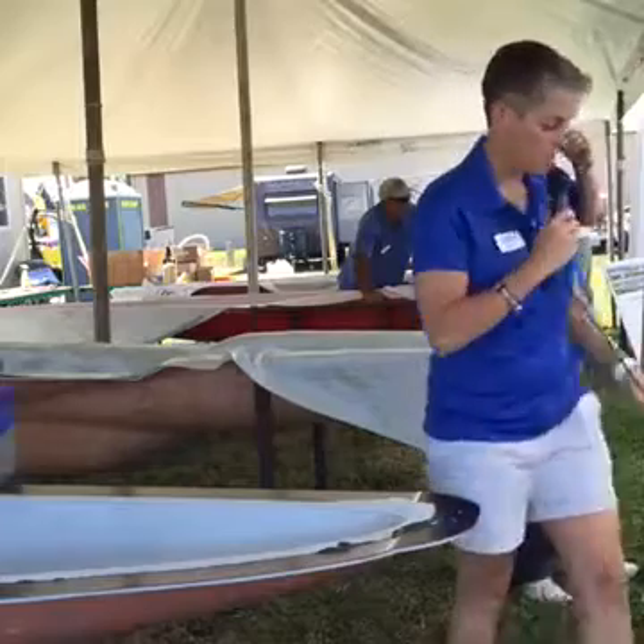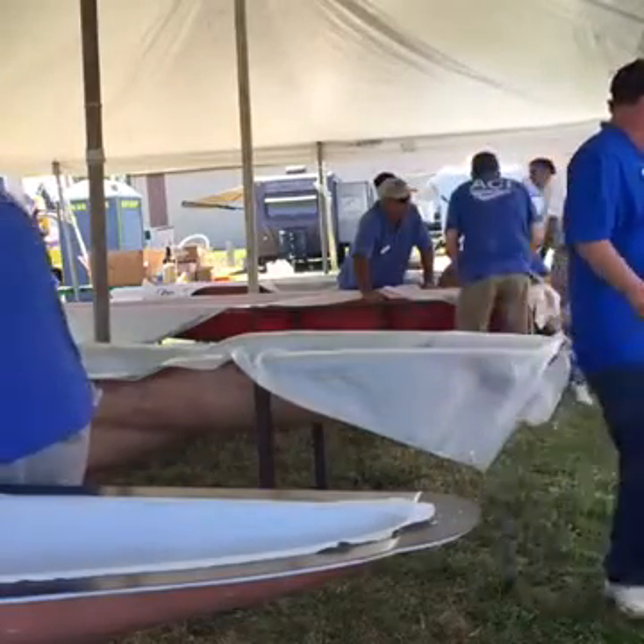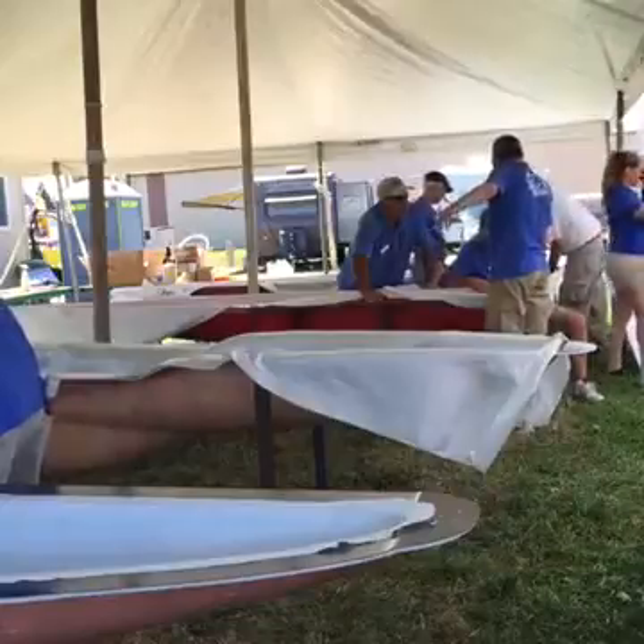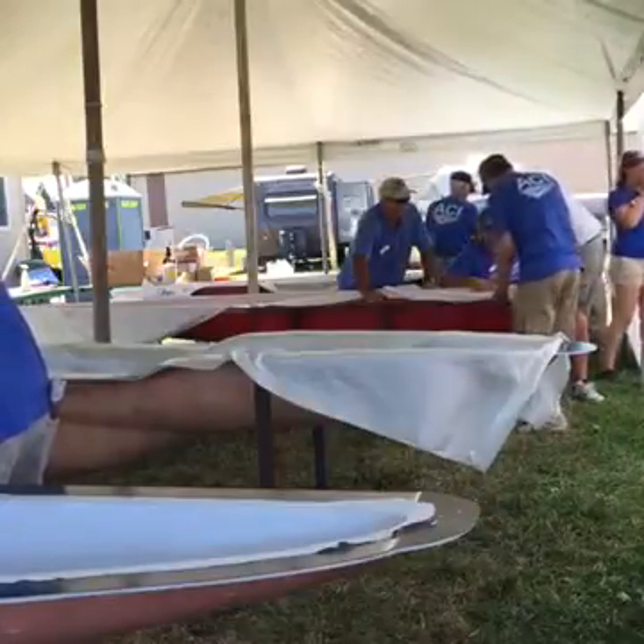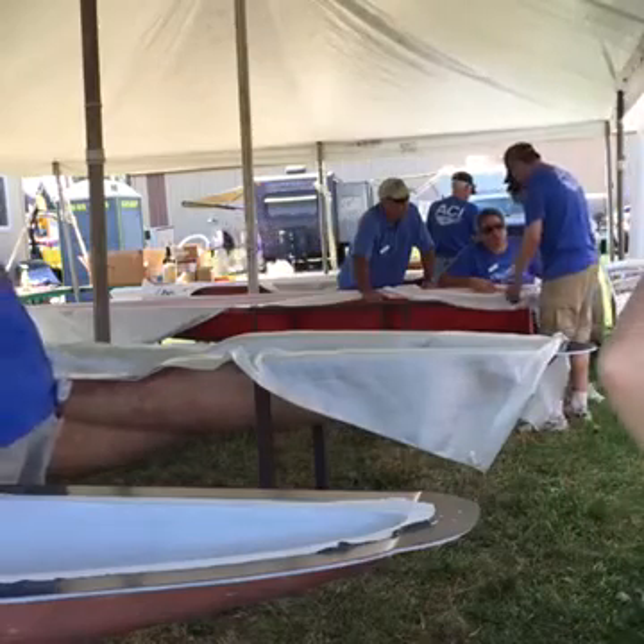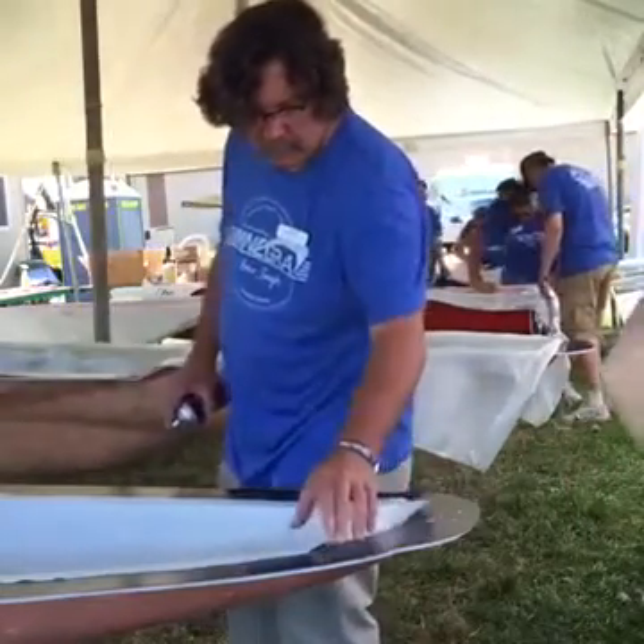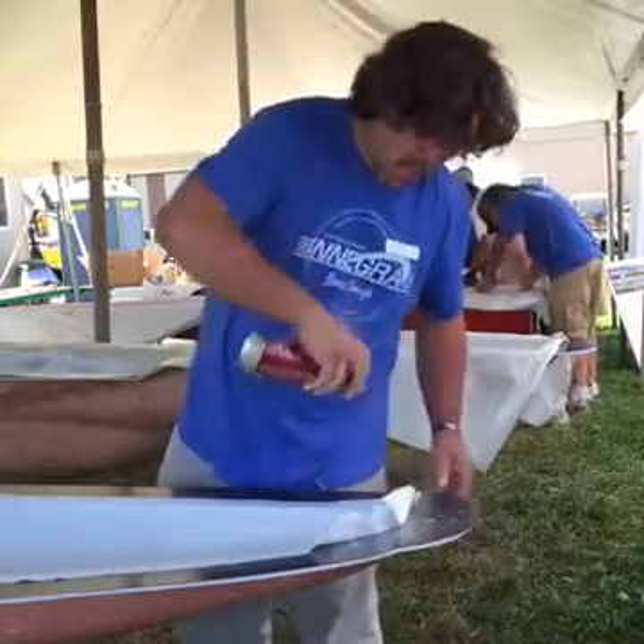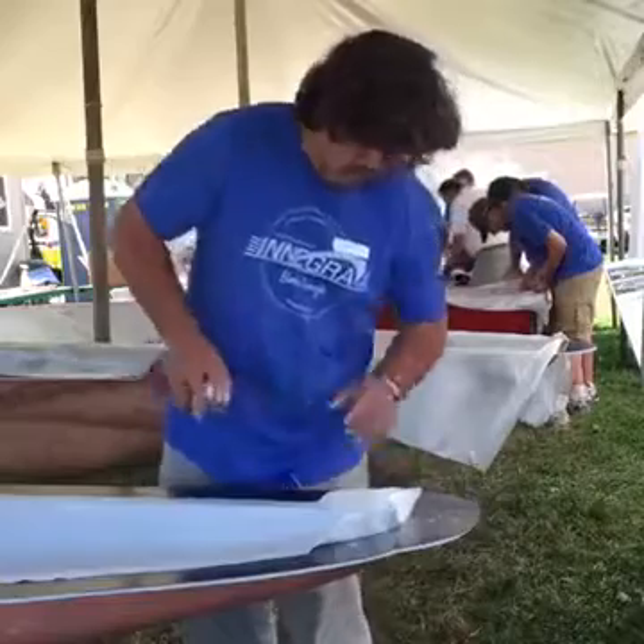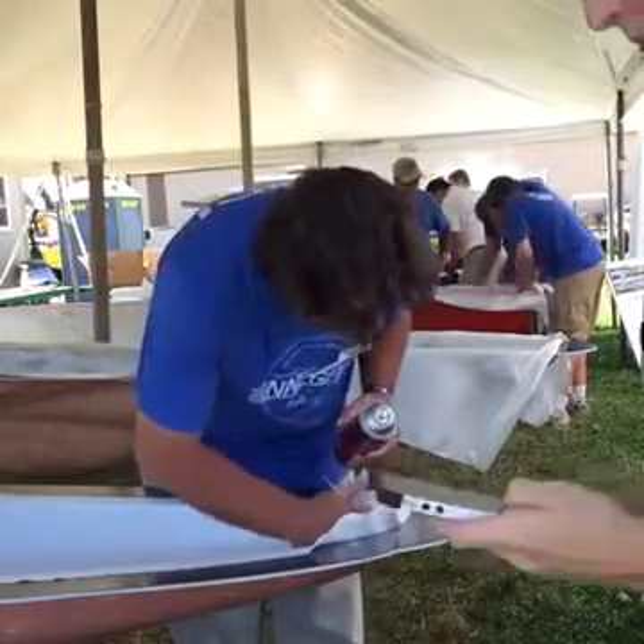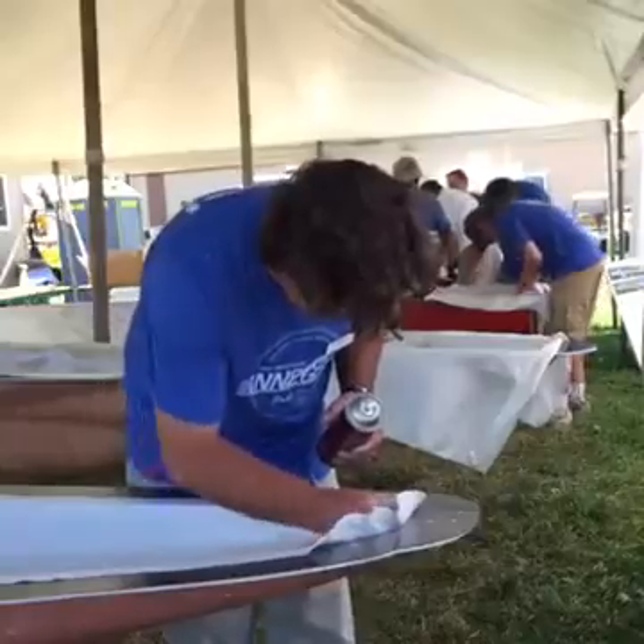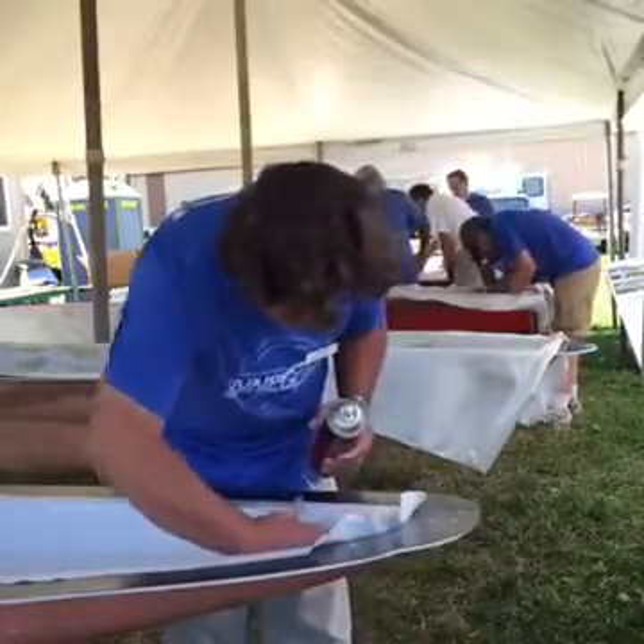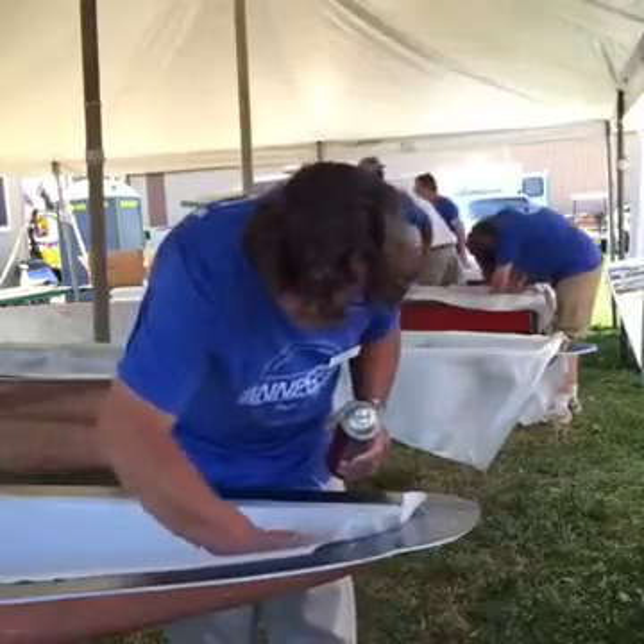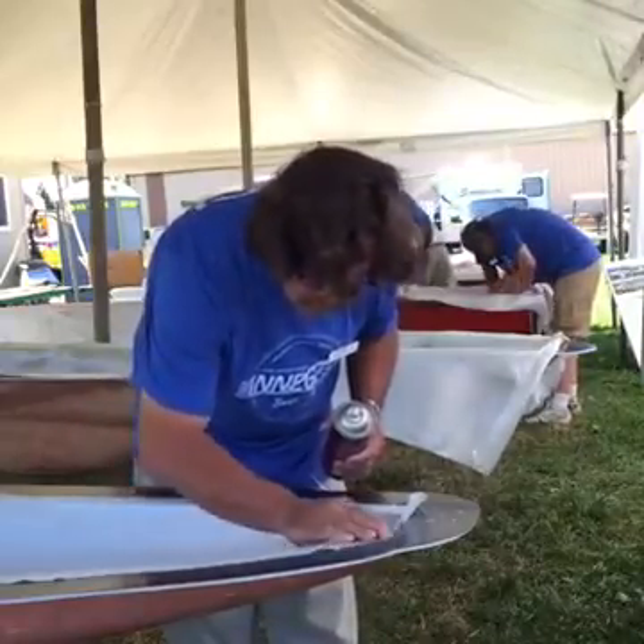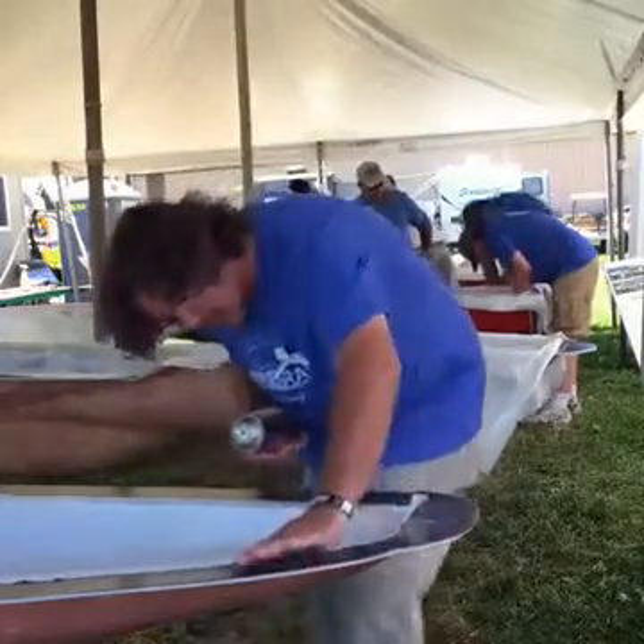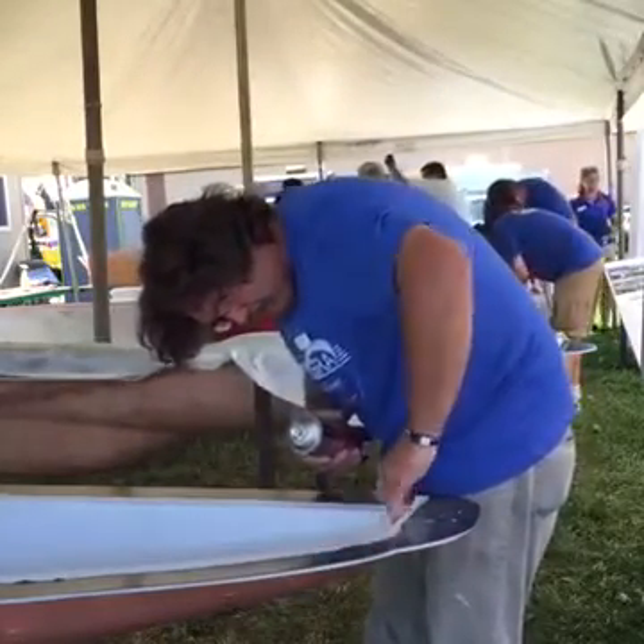All right, so single bag versus double bag. Single bag is normal processing, period. The process for double bagging was actually with Boeing and NASA back in the early 80s. The purpose of the double bagging back then was simply to control or prevent blown bags in autoclaves. If any of you are familiar with how autoclaves work, it's heat and pressure. So as you elevate the pressure inside the autoclave, you're dumping vacuum at the same time, to keep everything kind of evenly balanced. And then you're applying whatever pressure you need for that particular part's consolidation.